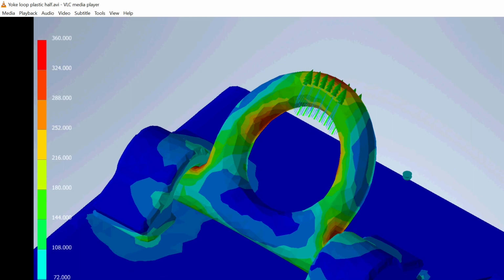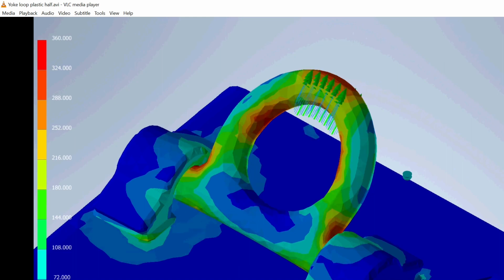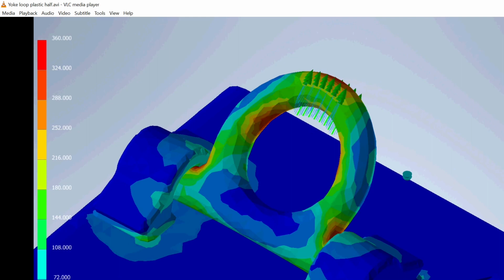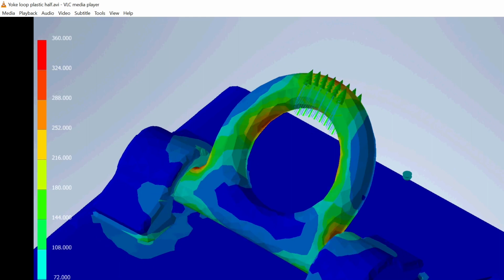But if you did a simple linear elastic simulation and you stay below 260 in this case for S355, then you know that you are within the endurance limits of the metal, and it will technically never fail as long as the loads don't exceed the design limits. So it's very easy to make a component strong enough for a certain load. The elastic simulations are completely, fully enough.